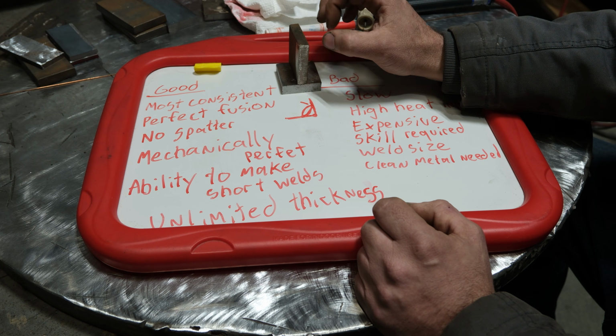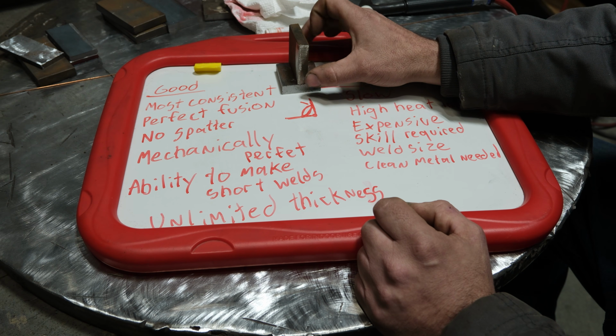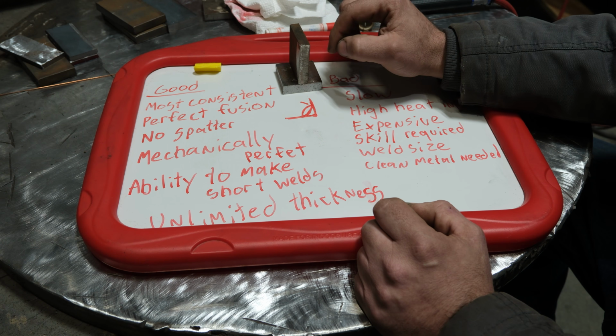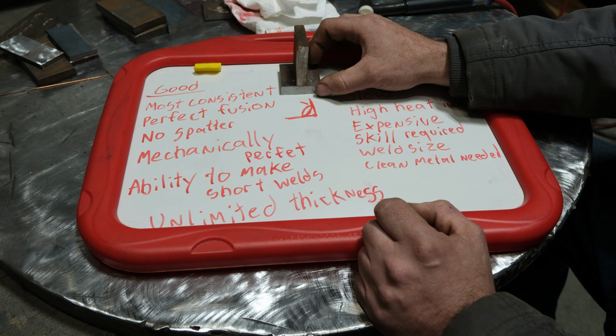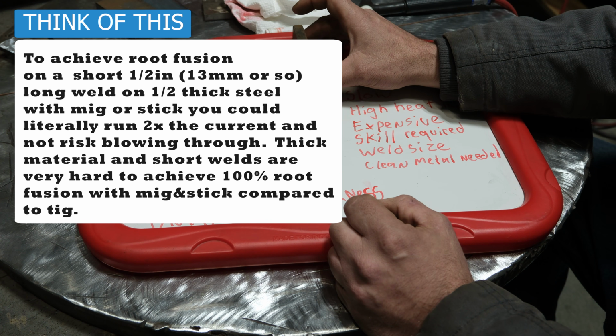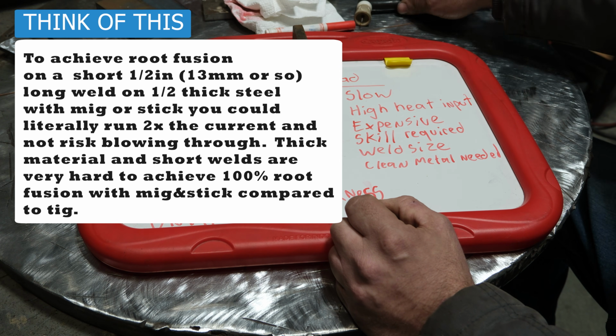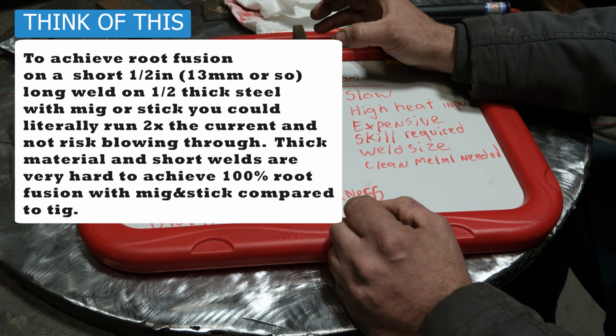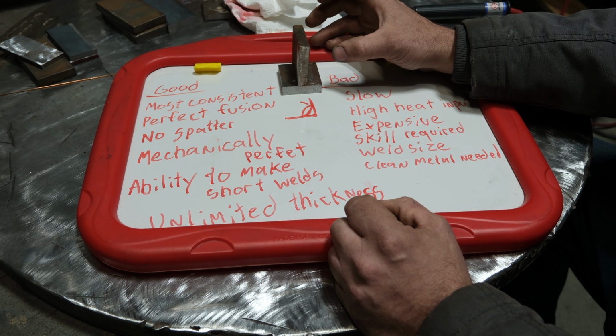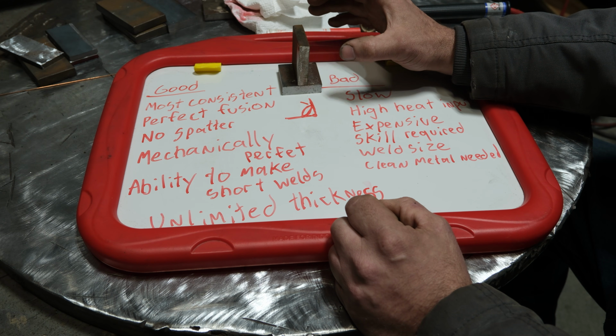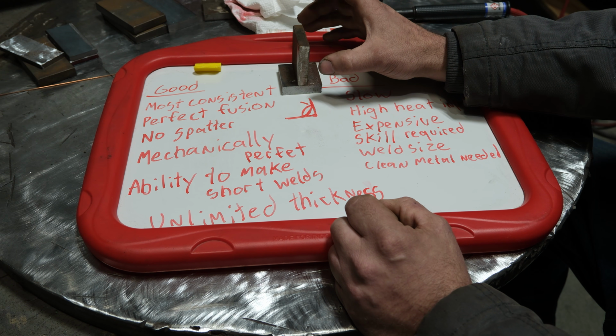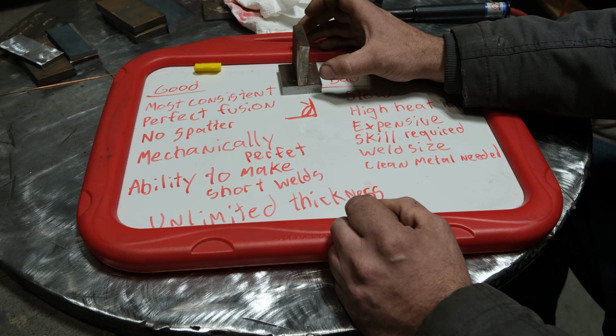So the ability of TIG to make perfect full fusion welds on very small components or very thick materials is a huge benefit. And that is why on a lot of widgets, like things that NASA makes and little small parts, TIG welding is often preferred, not just because of how clean the welds are, but because you can achieve things that no other process can, because again, your fusion and your filler material are two separate entities. With stick and with MIG, you're using your filler to pass an arc. Therefore, you have to consume some of the filler in order to have an arc. And the downside to that, like I said earlier, is that your fusion basically coincides with adding filler, and you will have lack of fusions at the start of welds with all other common welding processes. TIG, you don't have that issue.